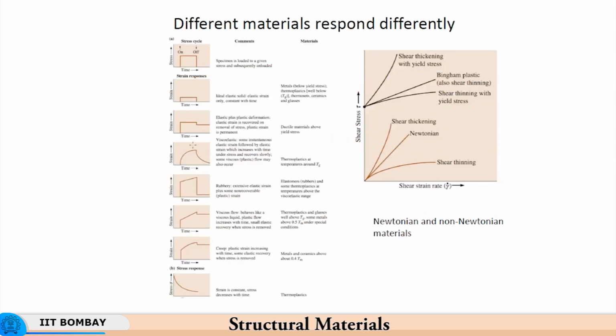So, you have instantaneous elastic strain followed by elastic strain which increases with the time under stress and recovers very slowly. Some plastic flow can also occur, meaning some permanent set in the material can also take place. So, this strain may not come down to 0, it may asymptotically remain at a certain strain level. So, some plastic deformation can be observed.